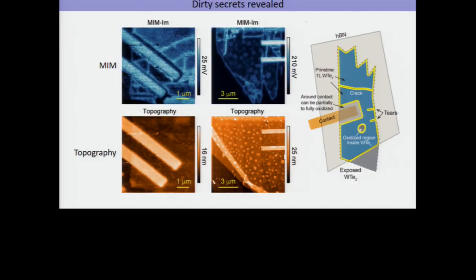Yeah, there was a question. Magnetic field in MIM measurement? I skipped the field measurements, but the conductance is suppressed somewhat. We can only do it at 4 Kelvin, so we don't expect a huge suppression of the edge. We can only go to about 4 Tesla at 4 Kelvin, but we see some suppression of the edges, and the bulk is completely unaffected by magnetic field.